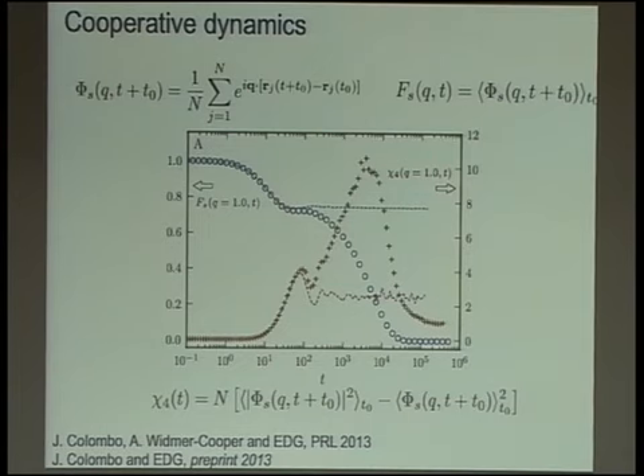Okay, and in order to quantify also this type of dynamics that develops in the network, one can look at the fluctuations of the average dynamics, so what is usually called the dynamical susceptibility chi4, which is given by the fluctuation around this average dynamics as it is measured by this type of relaxation function. And this, as you can see here, these are these crosses here. As a function of time, it develops a peak that again is very typical of glassy dynamics, and it's a peak that is located around more or less a time scale that is typical of the relaxation time of the network over this length scale, q equal 1.